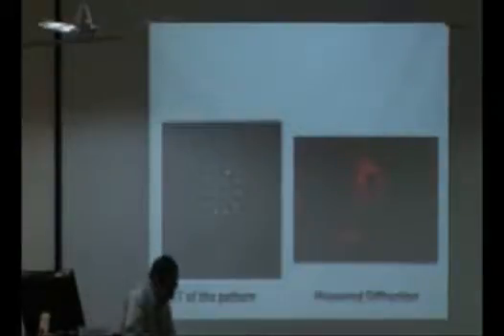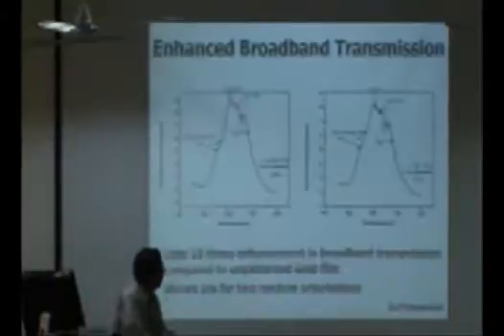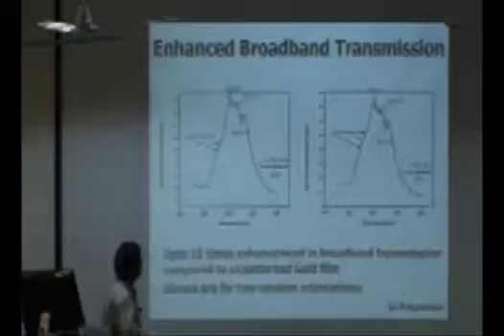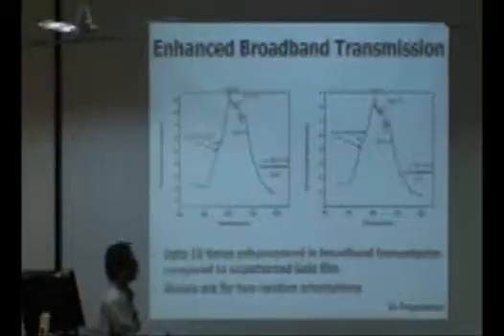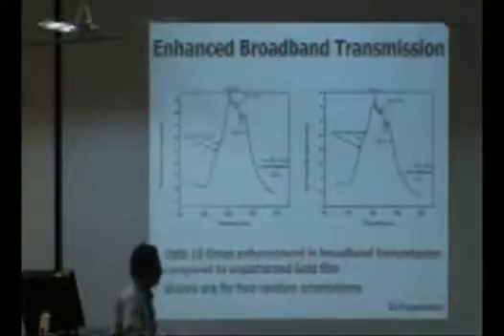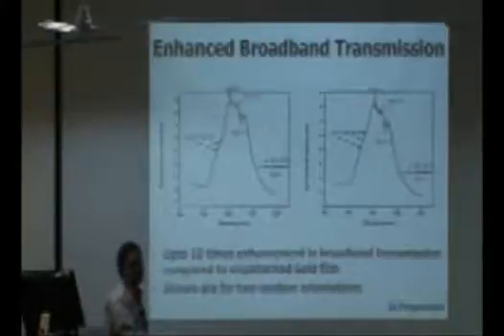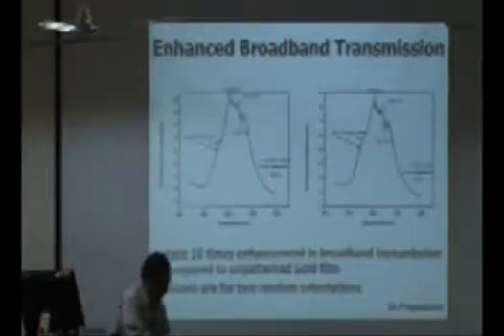Okay, we made these structures, and once we have this structure in real space, we can do the FFT to get the K-space structure and then compare it with the diffraction which we measure, which shows a pretty good match. We also use this information to calculate the plasmon modes which are theoretically possible for this structure. So what we have shown is that there is up to an order of magnitude broadband enhancement in transmission from these structures, and it's completely polarization and angle independent. In addition, we have seen some nonlinear properties like second harmonic generation, and we're trying to understand the origin of this.